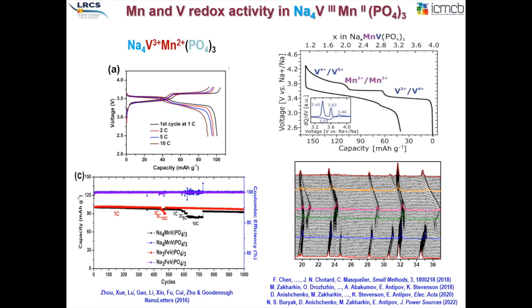And we indeed also worked on that together with a group in Russia as well, to demonstrate that 3 sodium could be indeed extracted from this Na4MnV(PO4)3 material. So this leads to a substantial increase of the capacity, but this also leads to a substantial change in the electrochemical voltage composition curves and shapes, with a very strong structural rearrangement upon the last sodium extraction phenomenon.